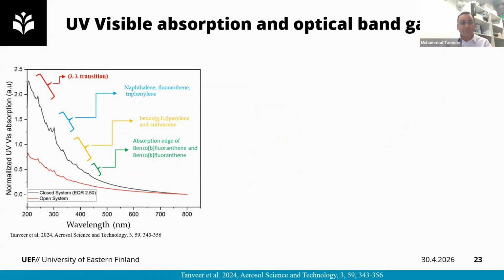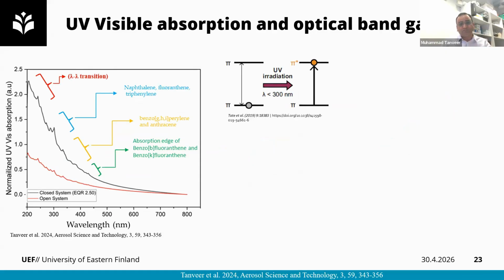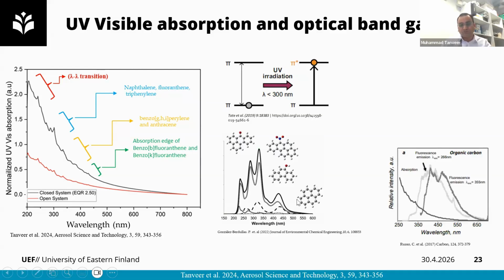Next, UV-visible absorption. Our sample shows different optical regions, like the intense blue region, and then the UV and visible regions. The intense blue region is basically due to the pi-pi transition, which happens due to high energy absorption and shifting of electrons from pi to pi star, and this shows this kind of absorption. In the visible region, we have observed different PAHs in our sample. These PAHs actually contribute to the absorption in this region. So these studies also confirm the presence of these PAHs, and polyaromatic hydrocarbons can contribute to the absorption in the visible region.